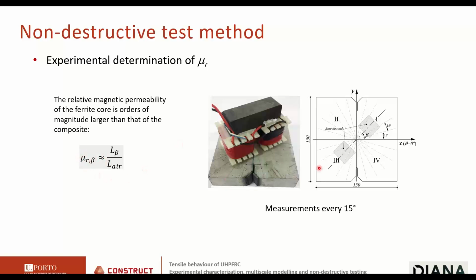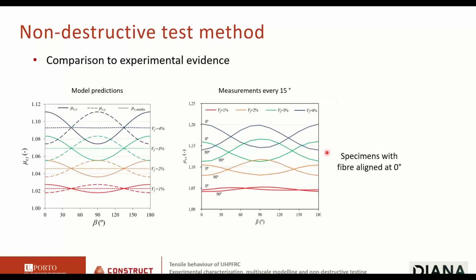The relative magnetic permeability of the UHPFRC can be obtained very simply by measuring the inductance of the circuit when the probe is placed in the air, and the inductance that is measured when the probe is placed over the UHPFRC. We took measurements on many specimens with oriented fibers and non-oriented fibers, every 15 degrees. This is what the theory predicts. Every 15 degrees, if I have a specimen with oriented fibers, I see higher relative magnetic permeabilities, and then they decrease when I am 90 degrees apart, and then they increase again.